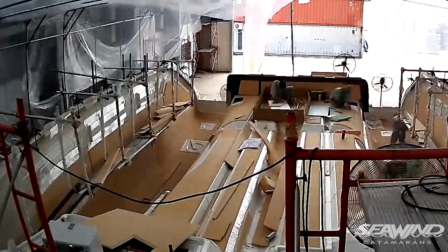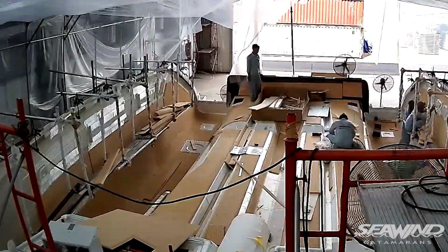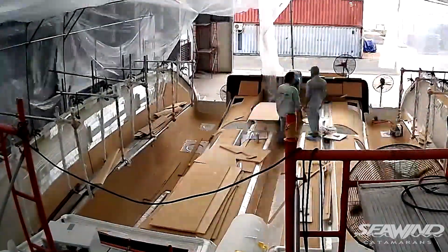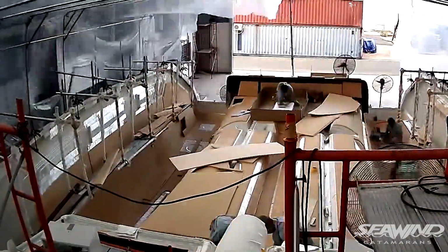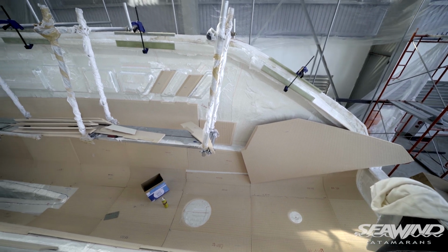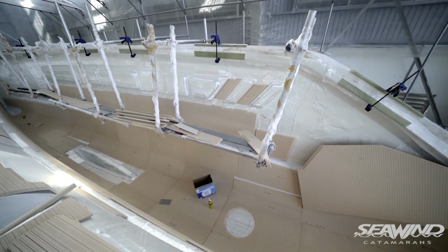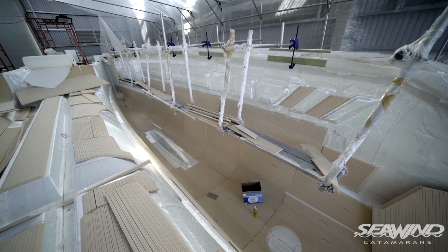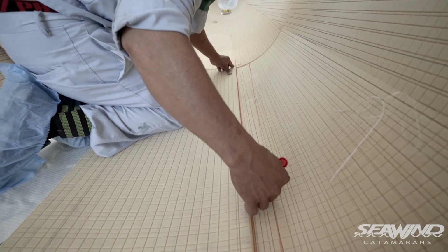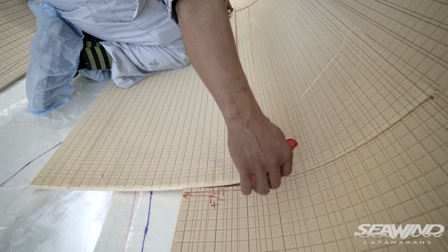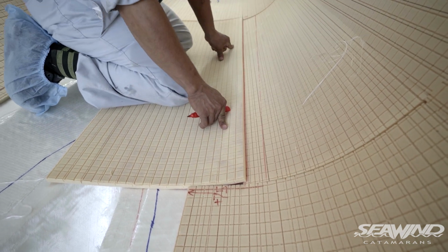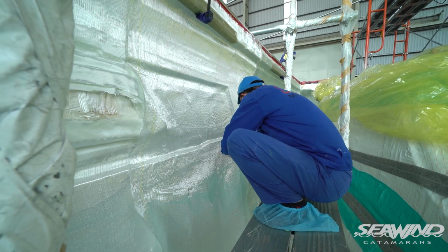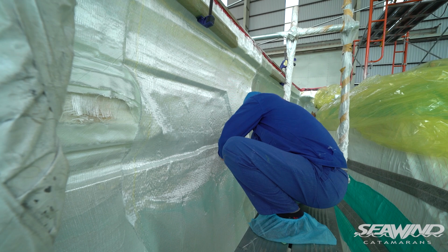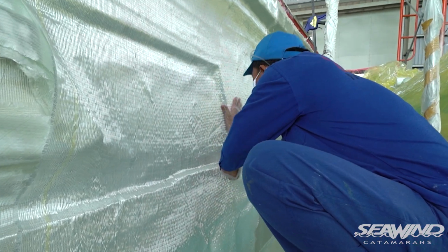When the outer skin laminate is in place, we'll start applying the foam core, and this gives us superior strength and stiffness to the hull and greatly reduces the amount of layers and fibres needed to achieve the same result. Our foam kits are pre-cut by CNC machines, so we receive the foam ready to load straight into the hull, saving us a lot of time and waste, and greatly improving our cycle time so we can produce the hulls faster. Our core foam also acts as a flow medium for the resin to pass through during the infusion process. Once the core is complete, we'll then add the final layers for the inner skin and any other additional strength patches and carbon beams.